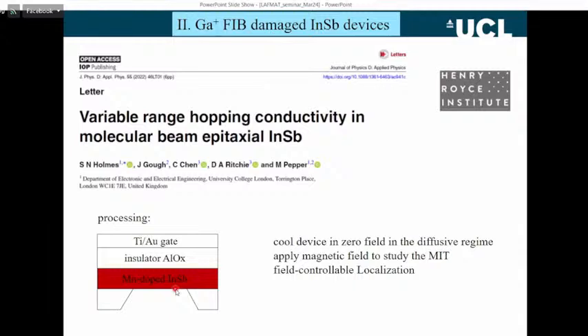We were hoping to get some suspended layers in this material, but we haven't developed the processing of this material system yet. And the indium antimonide is a narrow bandgap semiconductor. We put some manganese doping in there to make it p-type. Manganese is a p-type dopant in indium antimonide. And then we put down a layer of insulator and then a top gate. So with a gate voltage, we can induce charge at the surface or perhaps deplete the layer.